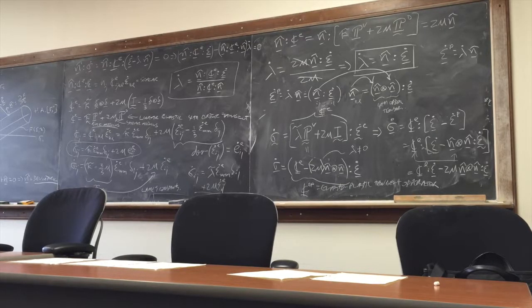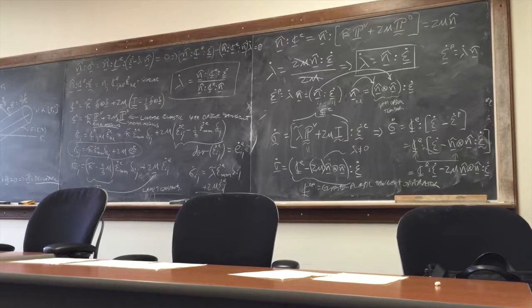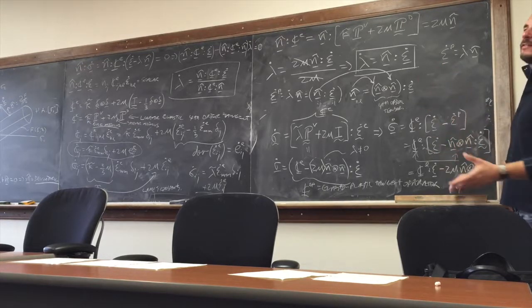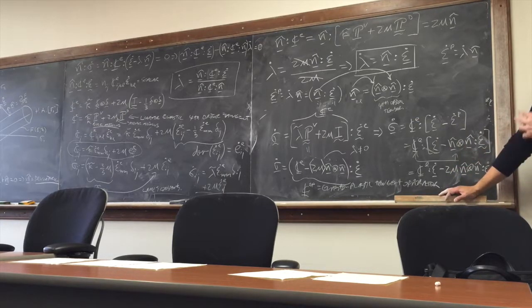And then once you digest this model, which is a simple model, the radial model, then the other models will essentially build on complexity. For instance, the next level of complexity is letting your radius expand or contract. The next level of complexity after that will be letting your cylinder float away from the hydrostatic axis. The next level of complexity will be forgetting about the cylinder and putting some more complex surfaces, and so on and so forth. But the principles are the same. F equals 0 all the time. Lambda dot needs to be consistent with your formulation. Hooke's law remains the same. The machinery remains the same. The geometry changes. And the geometry is dictated by this form of F and by the rules that you enable F to evolve by. And that's it. Every model is just a variant of that.